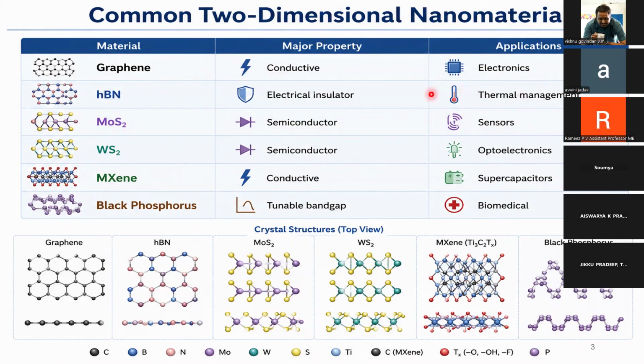mostly into HBN. The reason why I chose HBN was that even though it has a relatively high thermal conductivity, its electrical conductivity is too low. It is an electrical insulator. So you can use this material as a perfect substitute where you need thermal conductivity without being influenced by the electrical parameters. So mostly into thermal management.